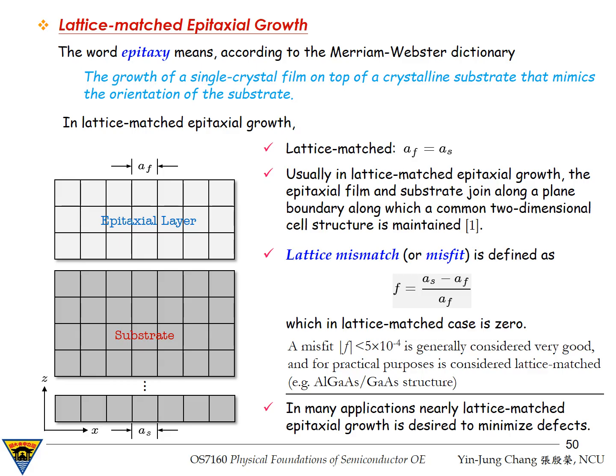At this point, you may wonder, why is lattice matching so important? Because lattice mismatch introduces strain. If the mismatch is too large, the film cannot remain coherently strained and will relax by forming dislocations. These are called misfit dislocations, and they act as non-radiative recombination centers in optoelectronic devices. In light-emitting diodes and laser diodes, dislocations significantly degrade efficiency and reliability. So in many applications, nearly lattice-matched epitaxial growth is desired to minimize crystalline defects.